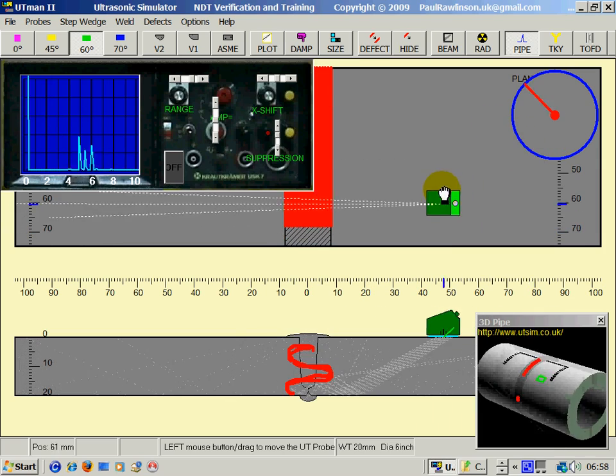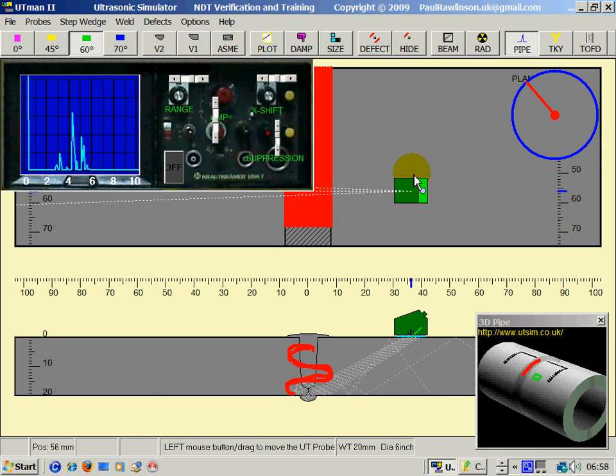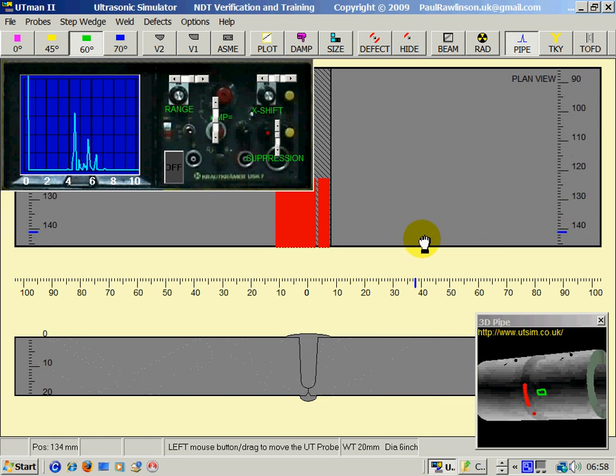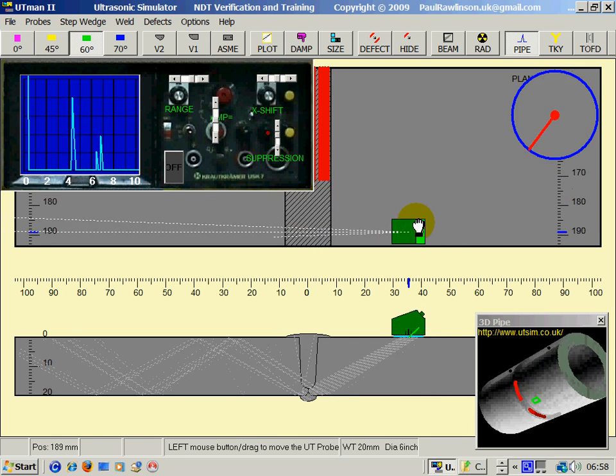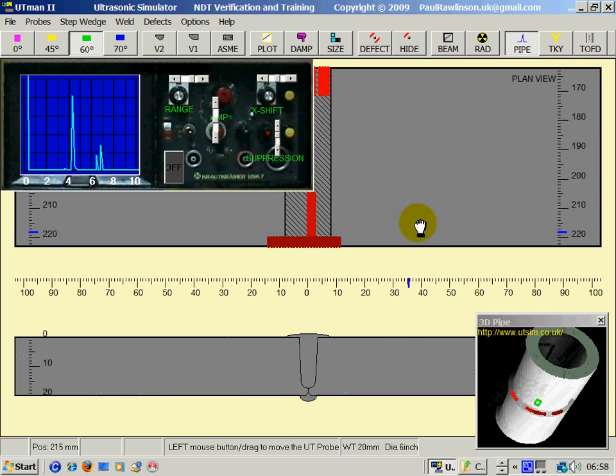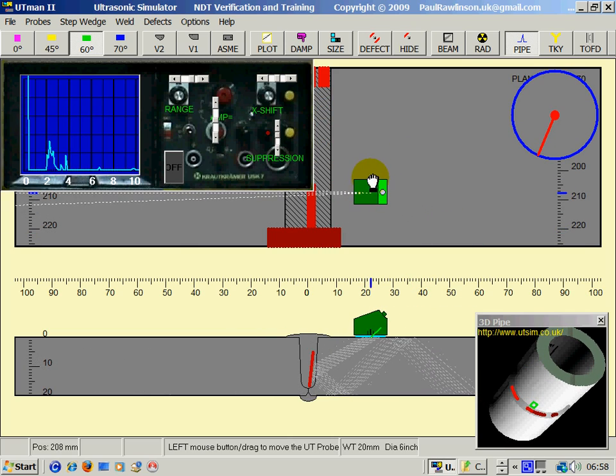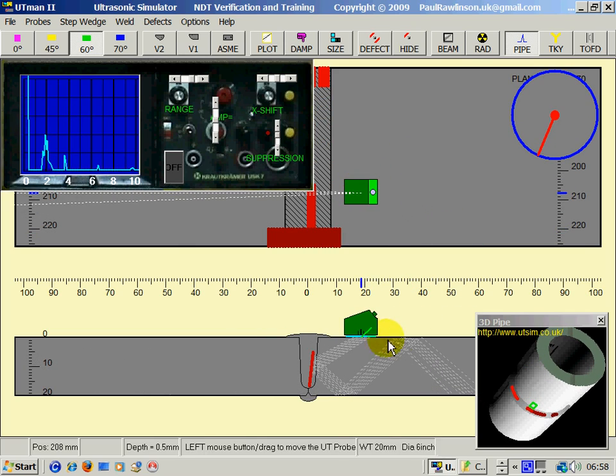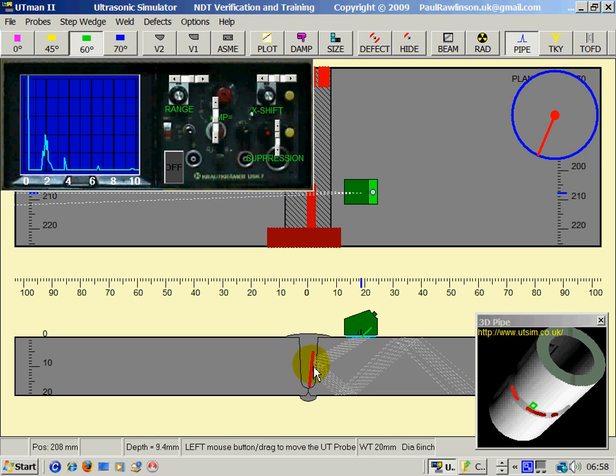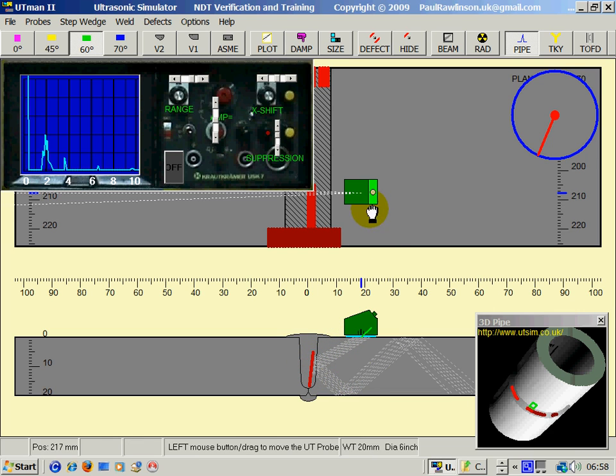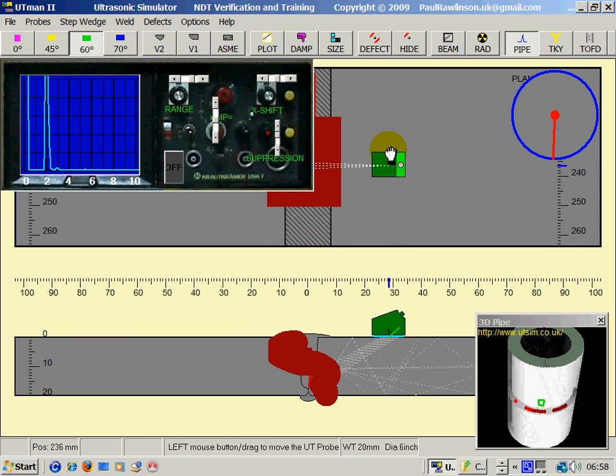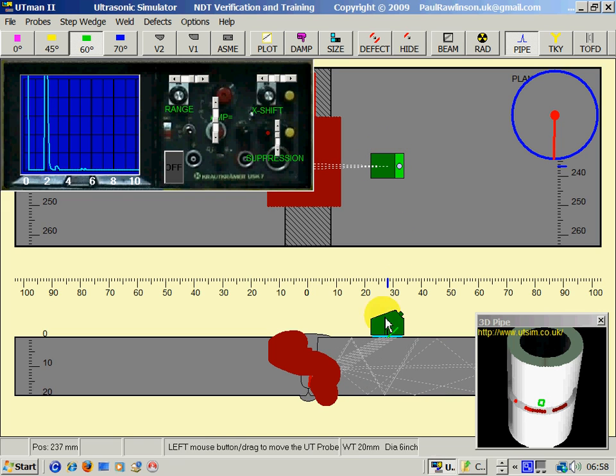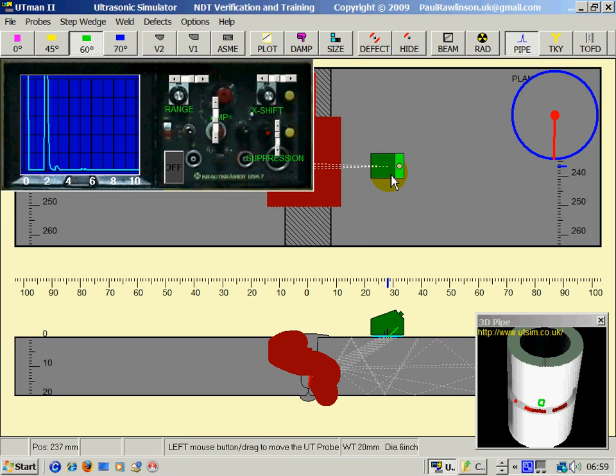By clicking anywhere it will stop the automatic scanning process. If we have a look at the lack of fusion defect, you can see the way the sound is evenly reflected off it, whereas a volumetric defect the sound is bounced all over the place.